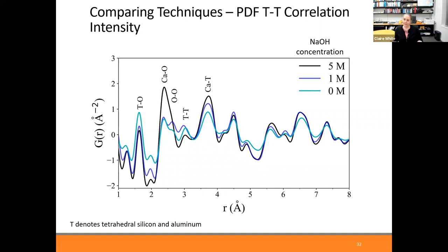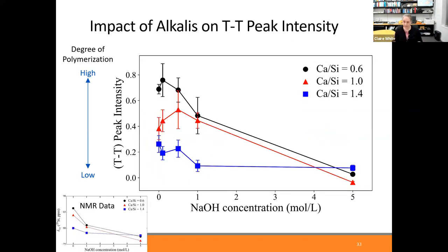What we did for fun was actually to take the intensity, so the Y value of this data here for this local peak, which is related to the distance between silicon-silicon and silicon-aluminium. And so if you have more of these distances that show up, we think it's an indication of the degree of polymerization of the material. And actually, what we found when we plotted these intensities is, yes, we end up with a similar plot to the NMR data. This is kind of cool.